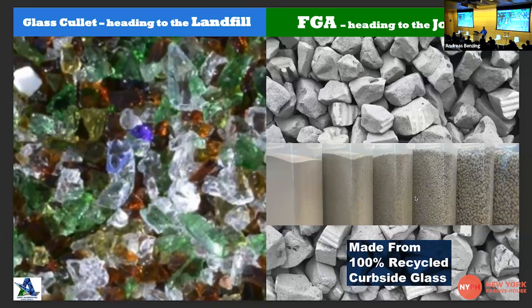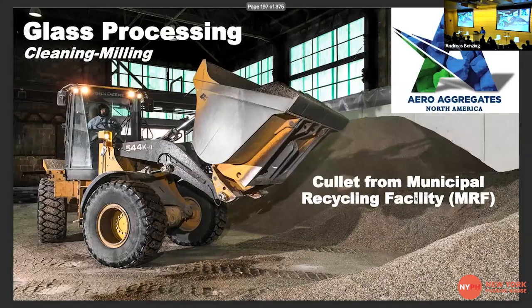So we're starting with a glass cullet that's destined for the landfill. As they're recycling glass, they're optically sorting it. Once those particles become too small to be optically sorted, this material goes to the landfill. 96% of this material is going to landfill nationwide. So you can take the glass cullet to the landfill, or you can do what we're doing. We're turning it into a functional aggregate and it's going directly to the job site.